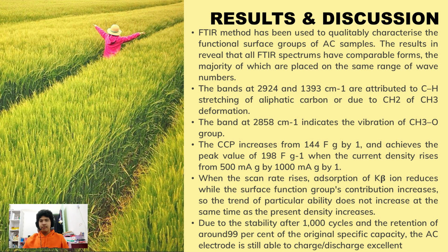The specific capacitance increased from 144 F per g and achieved the peak value of 198 F per g when the current density rose from 500 mA per g to 1000 mA per g. When the scan rate rises, absorption of K plus ions reduced while the surface functional groups' contribution increased. So the trend of specific capacitance does not increase at the same time as the current density increases. Due to the stability after 1000 cycles and the retention of around 99% of original specific capacity, the AC electrode is still able to charge and discharge excellently.